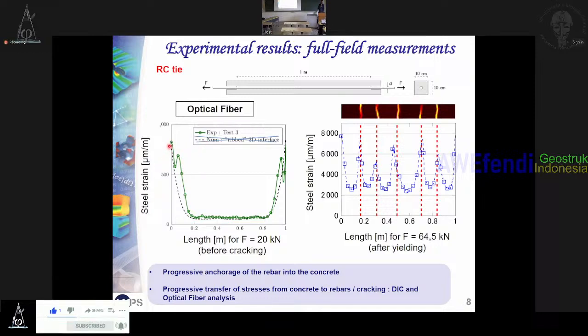Normally, as Dirk Schlicke has shown before, we should have a decrease, but here you have a small increase. It was due to cracking that occurred during the conservation of the specimen, without any applied force. After that, when you have cracks, which here come from digital image correlation, you can see a localization of the strain where you have these cracks. As Dirk Schlicke said just before, the force in the rebar goes into the concrete, but when the concrete cracks, all the force goes into the rebar.